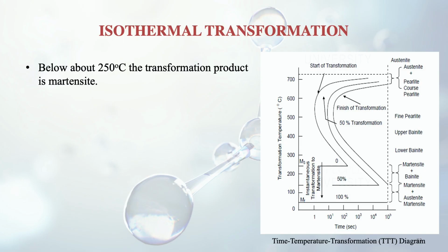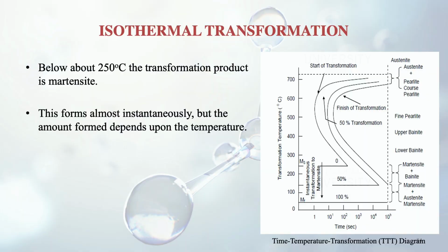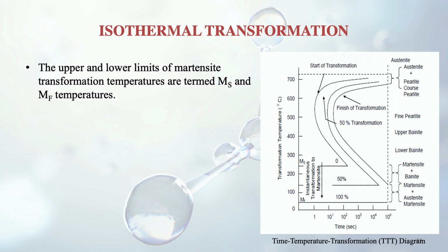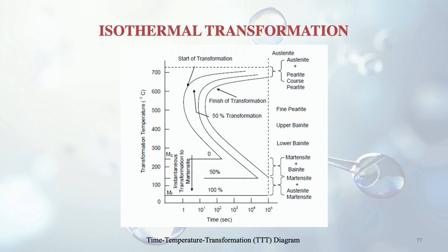Below about 250 degrees centigrade, the transformation product is martensite. As we know, if the quenching is done or the cooling rate is very high, then martensite is formed, and we reach the 250 degrees centigrade range. This is happening almost instantaneously, but the amount formed depends upon the temperature. So there are upper and lower limits of martensite transformation also, because the temperature at which it has started and the temperature at which it ends will govern this. The starting one is known as MS, martensite formation start, and then MF represents the martensite finish temperature. So from this diagram we can see how different processes of special treatments give us different things, like we discussed the Austempering and the Martempering.